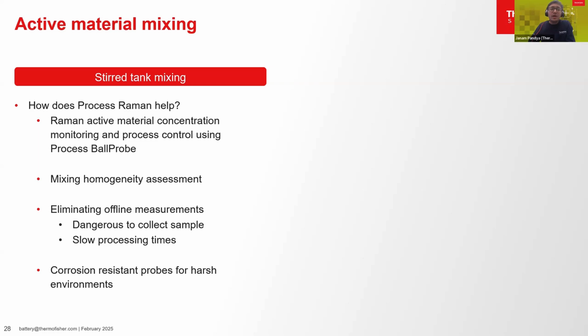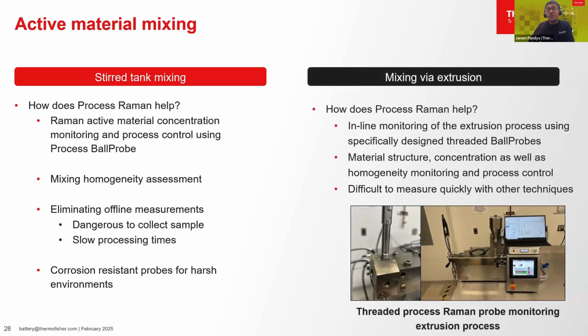Process Raman can also be instrumental in the active material mixing process, whether it is stirred tank mixing or mixing via an extrusion process. For the stirred tank mixing process, the process ball probe with Hastelloy construction can be used for continuous insight into the mixing homogeneity. Whereas in the extrusion process, a specifically designed threaded process ball probe can be used for in-extruder assessment of material structure, concentration, as well as homogeneity. Such inline measurements of the extrusion process can provide powerful insight into material characterization, distribution of binder, and allow better process control and improving overall product quality.